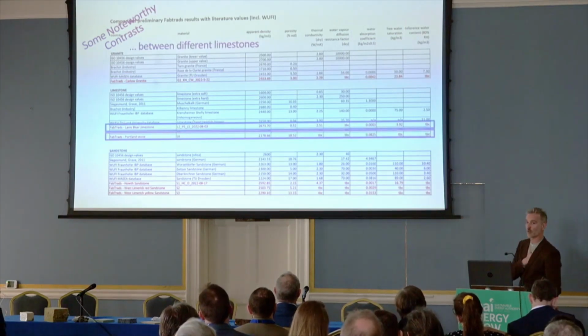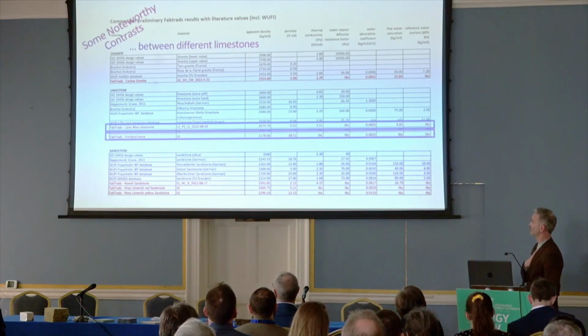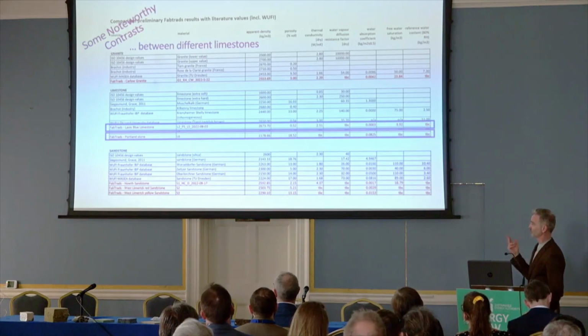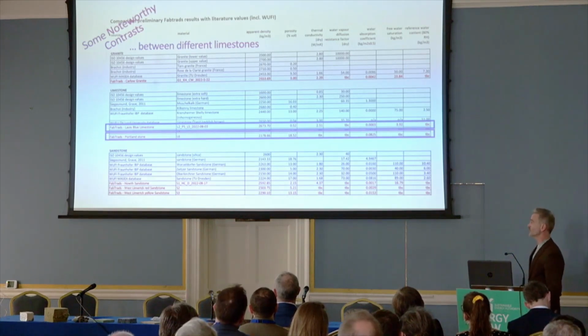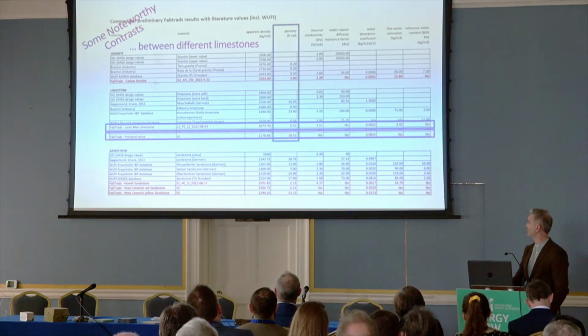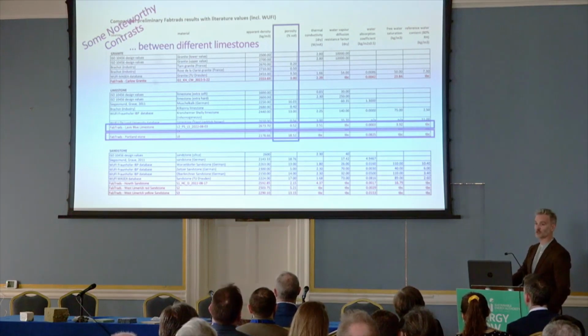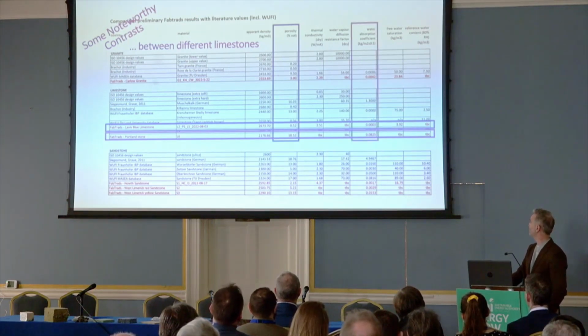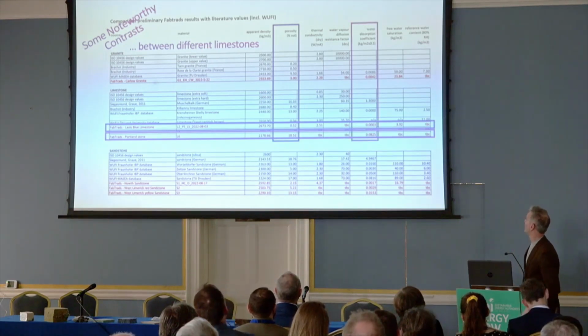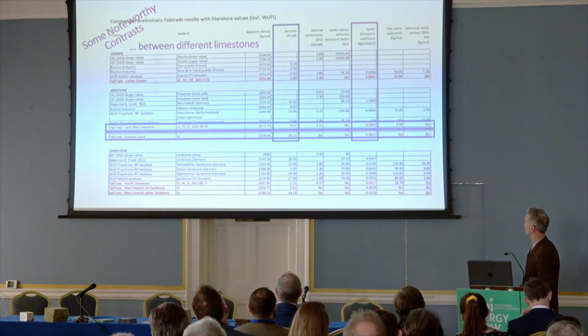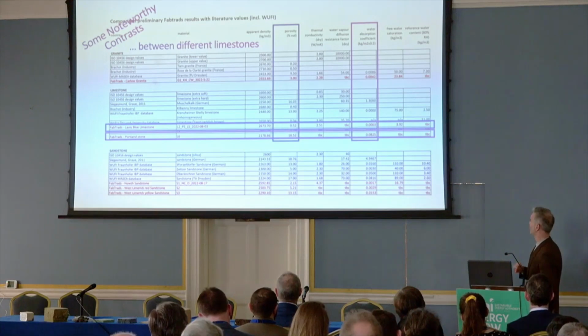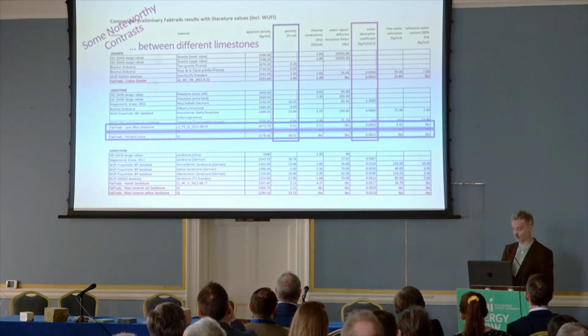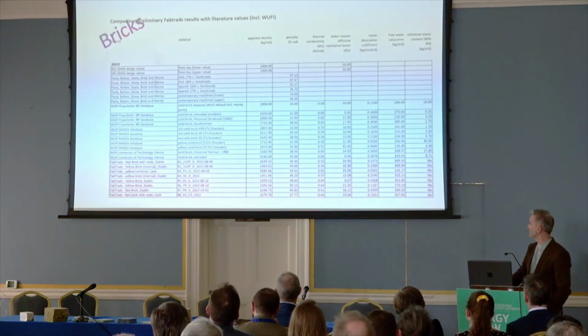Also, we're seeing quite a wide range of properties, even in the stone types that we're working with. If we look at two different types of stone, one being the Laois blue limestone, the other being Portland stone, a sample of which we got from the Customs House, a much younger stone, that shows much greater porosity than the Laois blue limestone. As a result, although not linear and quite strongly non-linear, we're seeing a water absorption coefficient that's much lower in the Laois limestone than in the Portland stone. And you'll also see that we're still waiting on other results to complete this data set.